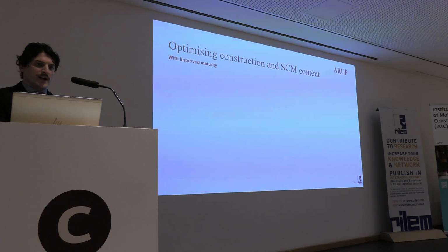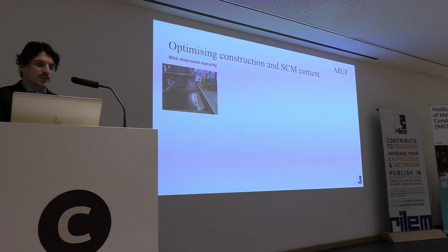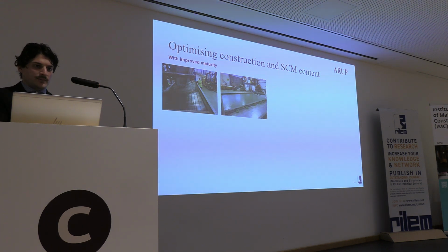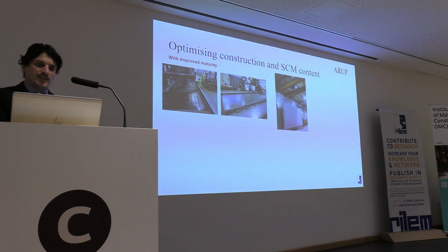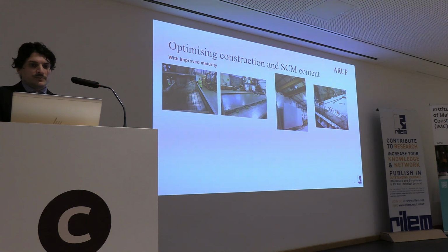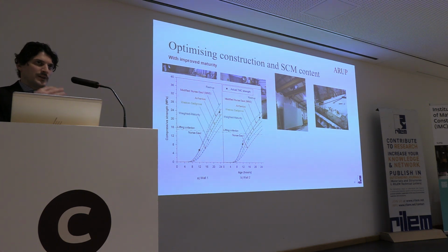So, okay, that's good in theory, but how did we demonstrate the application, and is this being demonstrated at the moment? This is a typical precast concrete factory where a slab, or rather a wall, is cast horizontally, and then is lifted after achieving adequate strength. But sometimes, because nobody really knows what the strength is in this kind of element, the strength can be below the lifting strength, and some deficiencies can occur, and damaged elements that are eventually rejected are generated. So we are able to produce this kind of very well articulated prediction of concrete strength, and to optimize the curing regime for precast concrete, but also maximize the use of supplementary cementitious materials in precast concrete, which is known to be quite carbon intensive, mostly CEM I being used in precast concrete.